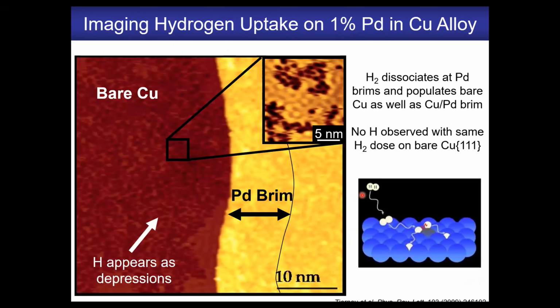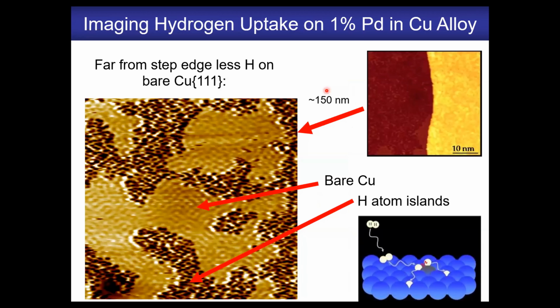So we can go look for hydrogen atoms that have spilled over with the 5 Kelvin scanning tunneling microscope. And this is an image showing that this is the region where the single atom alloy is with the palladium atoms above the copper step. And you see the whole surface is now covered in these small brown depressions, which are individual hydrogen atoms on the copper surface, even far away from the area where the system is alloyed. This is all pure copper, as you see here from the standing waves. You have these two-dimensional puddles of not molecular, because that would desorb, atomic hydrogen atoms on the surface.